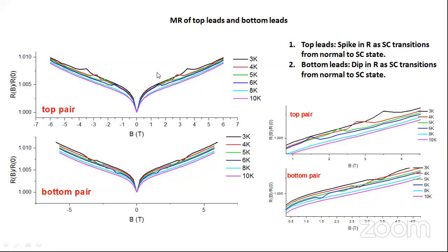There's a spiking behavior in MR, apart from the usual WAL that we expect in very low magnetic fields. And there is the opposite behavior that we observe in the low field. We were very skeptical about the results, and we checked this multiple times on multiple samples. Even on flakes we've done this and we observed the same results. So it's not because of inhomogeneity in thickness or anything of that sort. This is a true behavior.